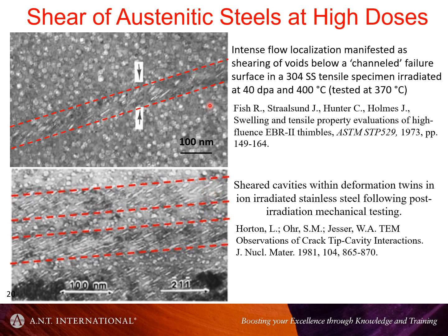So irrespective, however you look at it, whatever creates this, it's a bulk shear, and under those circumstances, it's very unlikely that you're going to get one cavity being sheared and moved on top of another one, so that you increase coalescence and somehow get some stress intensity, well, a crack formation. Highly unlikely. I don't think so.